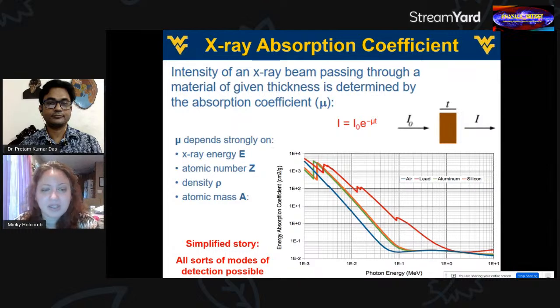And I'm not going to talk about all of them. There's a bunch. But just to give you a rough idea, I'm going to talk about a simple idea of just taking your X-rays and looking at how they get absorbed into your sample of some particular thickness. You can see here I have several different elements shown. As we change the energy of these X-rays, so that's one of the specialties of these synchrotrons, they have a wide range of energy that their X-rays can be, which they can control by adjusting the curvature of the path that the electrons are being accelerated around.